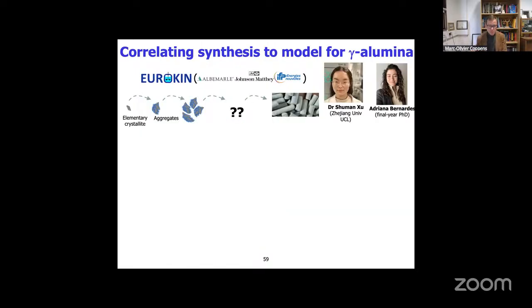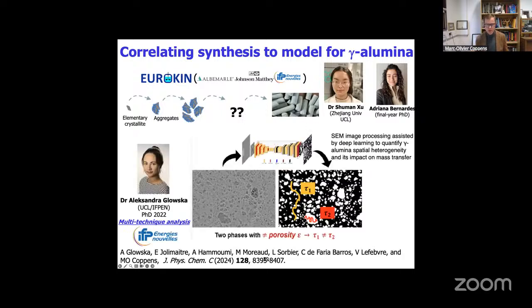So finally, to end where I started, we try to move towards a situation where we can correlate the synthesis of materials to the models of these materials, say for a material like gamma alumina. This is something that I'm very interested in, and we've been working in the context of a Eurokin consortium, sponsored by Axens, Johnson Matthey and IFP Énergies nouvelles, who've been interested for a long time in how elementary crystallites relate to the final morphology and the structure of porous alumina particles. And so this is clearly important to construct models for diffusion in them. And so, recent work: a seminar would not be complete nowadays if you don't mention machine learning and AI tools.